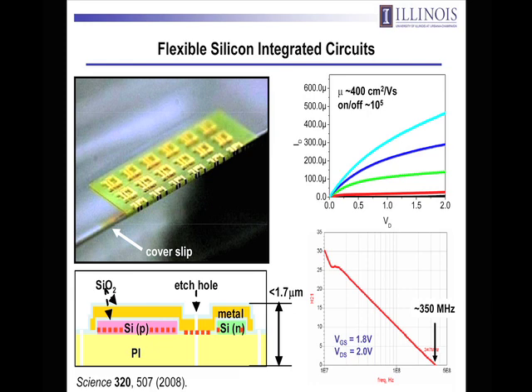This is a piece of CMOS silicon circuitry, a very simple device, just inverters, printed onto a very, very thin sheet of polyimide. So we're just pushing the thickness down as far as we thought we could go comfortably, a little bit over 1.5 microns in total thickness. And as a result of the thin overall thickness, the thin geometry of the silicon nanomembranes shown here in a cross-sectional schematic illustration, you can bend this thing to incredibly small bend radii, in this case about 25 microns corresponding to the sharp edge of that cover slip. So just making everything thin makes it bendable.